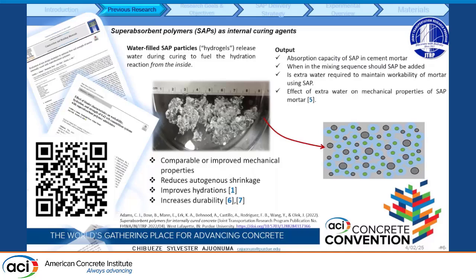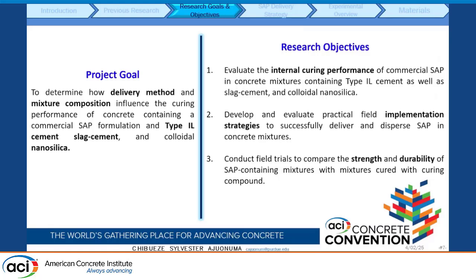Some of the questions we also get is, do we need extra water when adding SAP? We were able to find out that you can add SAP without adding extra water. We also found out the effect of extra water on the mechanical properties. From the research, we found comparable or improved mechanical strength. It reduces autogenous shrinkage, improves hydration, and increases concrete durability.